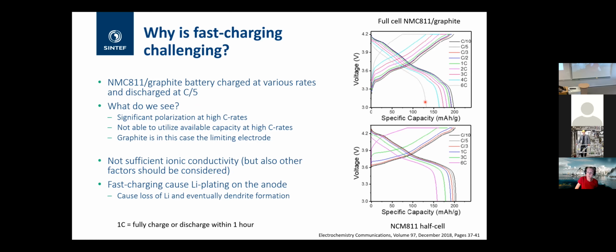And in this case, which I also included here, this is what we call a full cell with the cathode and a graphite. Here, they've done just what's termed a half cell, meaning that you cycle the cathode material against a lithium metal. That shows that you have much lower polarization, and you also have a less dramatic loss of capacity. That indicates that in this case, it's the graphite that's the limiting electrode for the rate when you fast charge. Not in the capacity sense, but for how fast you can charge and discharge your cell.